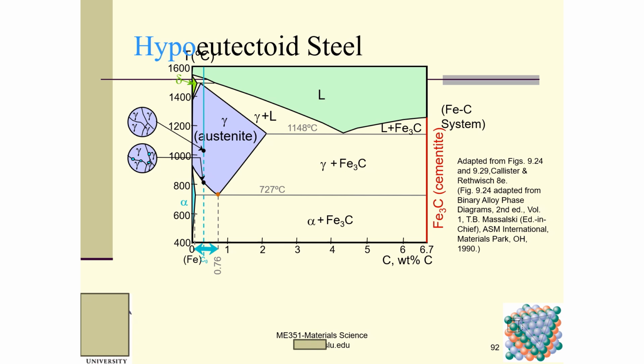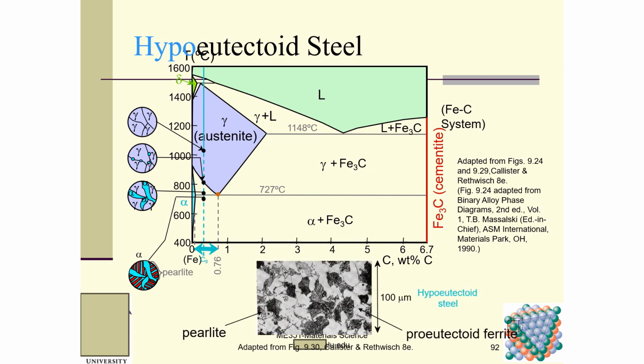And then we have these dots. The alpha dots grow, and then we have pearlite. This is pearlite, which means this is the lamella. The dark area here is alpha, which is the pro-eutectoid ferrite.